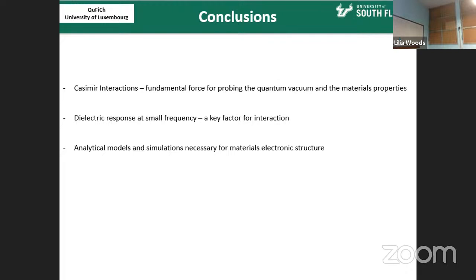forces us to consider a distance-dependent Coulomb interaction associated with the dimension of the film. And that presents some complications, and it introduces non-locality. So it introduces a wave vector dependence in the plasmon simply because it has finite thickness. And that's also related to the distance between the two. So the response of the medium depends on the exact electronic structure, the chirality of the nanotube. There is already a tool to do this.